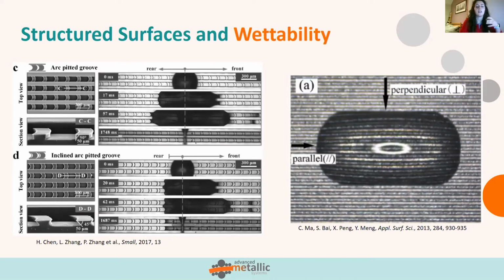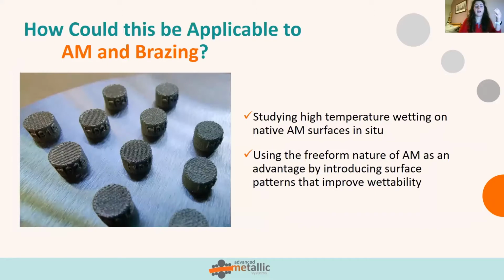So theoretically, this could be applicable to braze alloy systems as well. You can even see in a much more simplistic system, which looks at the spreading of liquid over straight channels, that there's a preference for movement in the parallel direction compared to the perpendicular direction. So how could this be applicable to brazing and additive manufacturing? What I'm doing is hoping to study the high temperature wetting on native additively manufactured surfaces in situ.